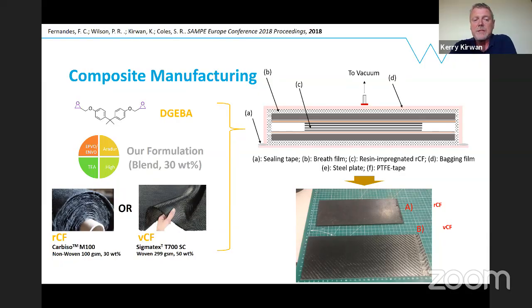So Carbiso is an off-the-shelf product now. You can buy that. It's a non-woven, 100 GSM needle felt mat sort of thing, and also the virgin carbon fibre, which is the industry standard Sigmatex there. And you'll notice that the grams per square metre are a lot higher in that, and that's important when we come on a bit later on another slide.